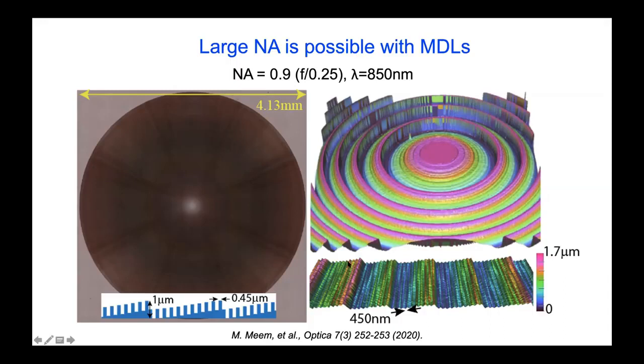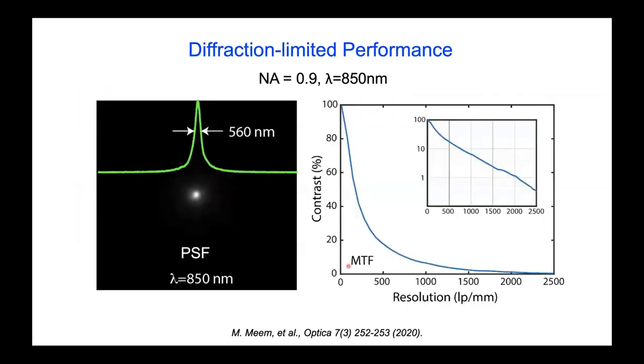But because we do not require very high refractive index for the final device. And this is simply showing a measured point spread function of that previous lens, which shows very tight focusing and so on. The MTF is shown here for comparison. You can get several thousand in terms of line pairs per millimeter, as expected. So it follows the theoretical prediction quite well.